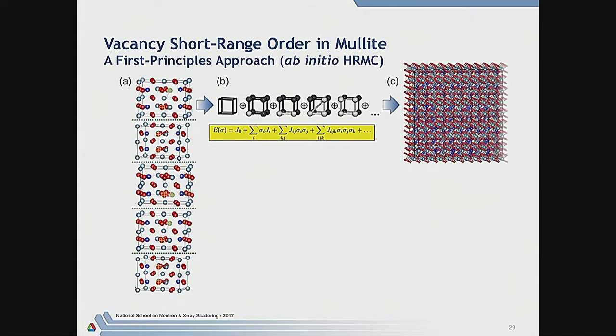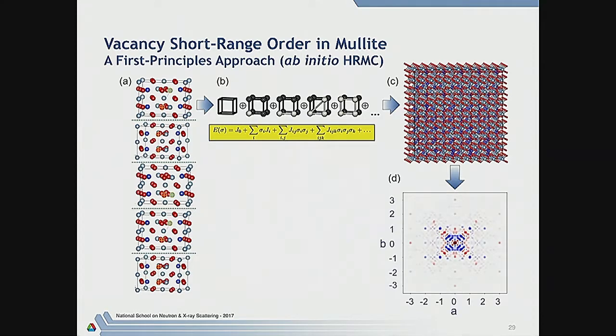And that allows you then to do a Monte Carlo calculation of a very large cluster, like 25,000 atoms, showing what the distribution of the atoms would be in that. And from that, you can then determine things like the pair distribution function. What is the probability that if you have a vacancy at one point, that you have another vacancy at another point? This is now in real space, A and B. And from that, you can then calculate the diffuse scattering.